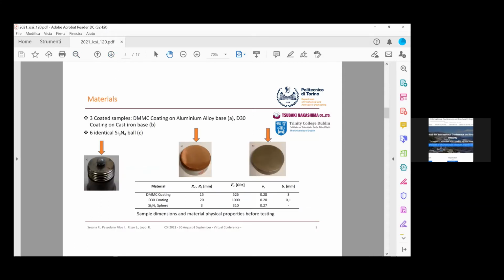The experimental investigation involved the use of silicon nitride ceramic balls with a nominal diameter of 6 mm and 2 different diamond coatings employed in pin-on-disc test. A diamond-reinforced metal matrix, indicated as DMMC, and a synthetic diamond coating with a maximum particle size of 30 micrometer, indicated as D30. Sample preparation was carried out in collaboration with Politecnico, Tsubaki Nakashima Internal Application Laboratory, and the Research Center at the Trinity College. A set of 6 nominally identical silicon nitride bearing balls was employed for the investigation and was retrieved from the production line at Tsubaki Nakashima.